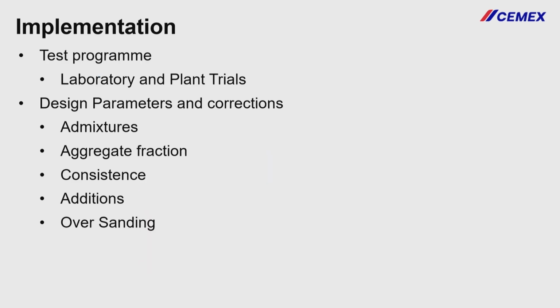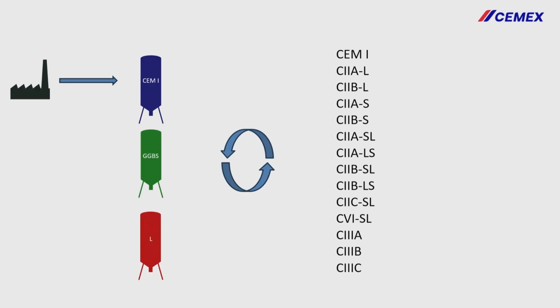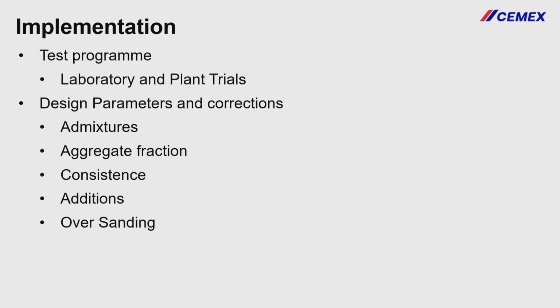But there's an awful lot of work that went into this. There's a slide missing, apologies. So the MPA, Mineral Products Association, MPA Cement, commissioned a study at the BRE into 25 different cement combinations. That was a 2-year study. We looked at carbonation, sulfate resistance, of course compressive strength, chloride migration, freeze-thaw resistance, very important obviously in this room, and also alkali silica reactions.